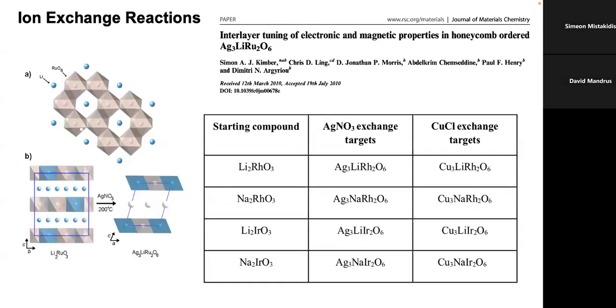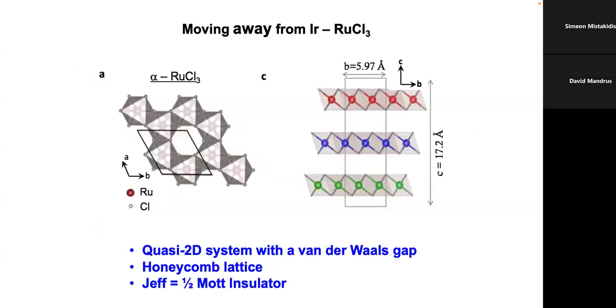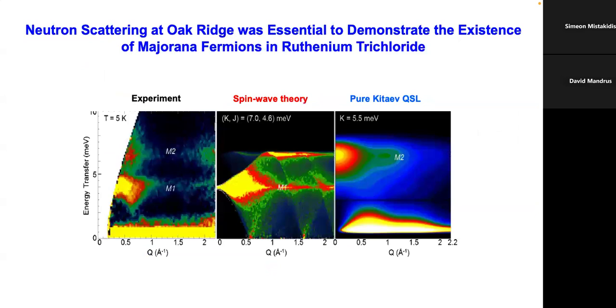And this has continued to go on with ion exchange and reactions. We replace things like lithium with silver, or lithium gets replaced with copper. And again, you make disordered quantum spin liquids. So those are not that attractive. And so people started moving away from iridium, and one of the ones they considered was ruthenium trichloride, and we worked a lot on this. So ruthenium trichloride is quasi 2D, a layered material, honeycomb lattice, J effective 1/2.